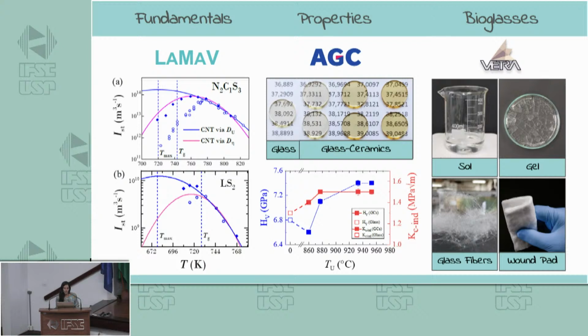As particular examples of each one of these topics, I would like to mention this study on the left, in which we found that the effective diffusion coefficient for crystal nucleation is best estimated from crystal growth rate data than from viscosity. This is important because it can allow us to give a better description of the nucleation process through models or theories, such as the classical nucleation theory.